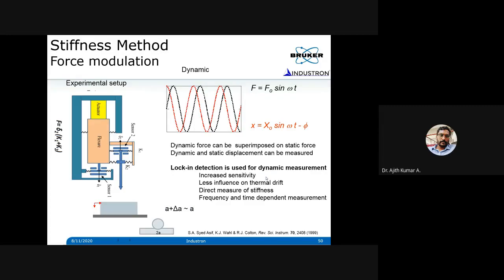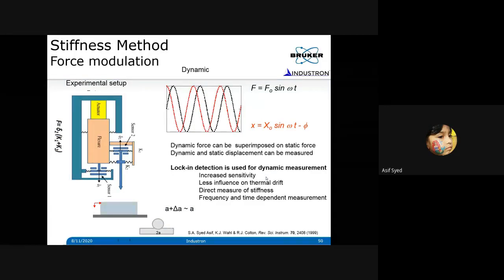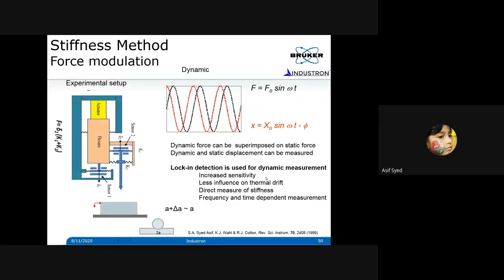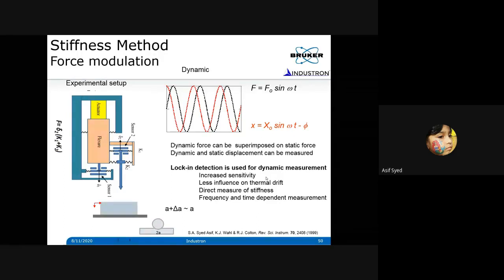So, yes, sir. Okay. So in this, one thing that I wanted to extend to stiffness-based measurement, I mentioned that you can also apply the method. The method that I mentioned so far is quasi-static, which is basically applying a continuous force in a quasi-static manner and measuring the displacement in a quasi-static manner. In the dynamic method, what you do is apply a sinusoidal force and measure the sinusoidal displacement. And from the force that you apply and the displacement you measure, basically the phase shift between these two, you can see whether the material is behaving in a viscoelastic manner or not.